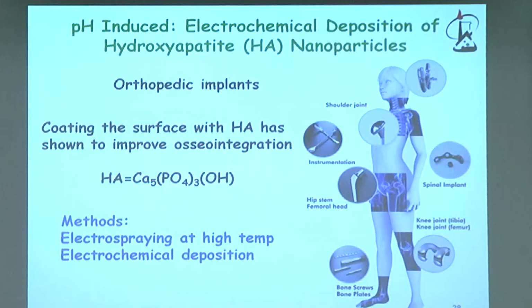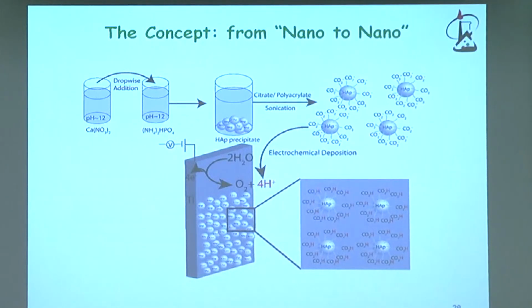The problem with this titanium is that it does not have this property. It doesn't cause the bone to grow, and because of that, nowadays what normally is done is that they take these titanium implants and they coat them with the main component of the bone, which is hydroxyapatite. And this is a very, very sophisticated process. It's done at very high temperature, above 1,000 degrees, by electrospraying, and obviously you cannot introduce by that any organic material. So again, how can we do that? We synthesize nanoparticles of hydroxyapatite, which have very low solubility, and we stabilize them in order to prevent their spontaneous aggregation.